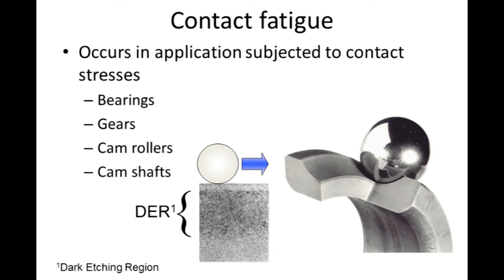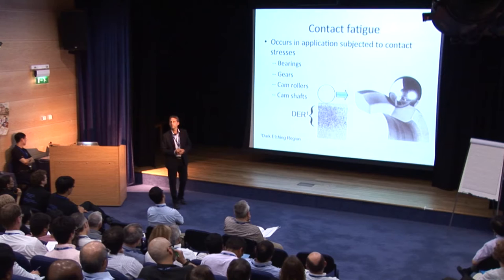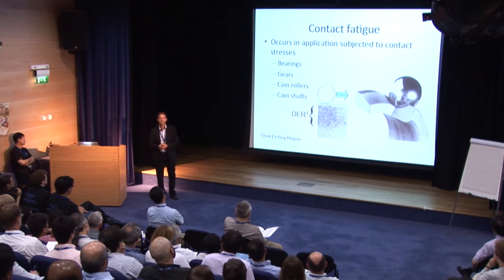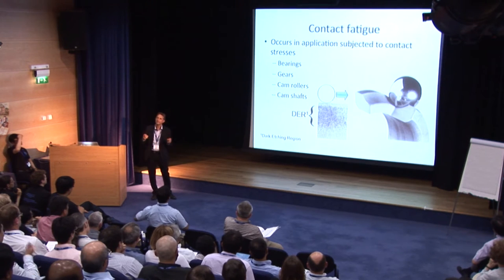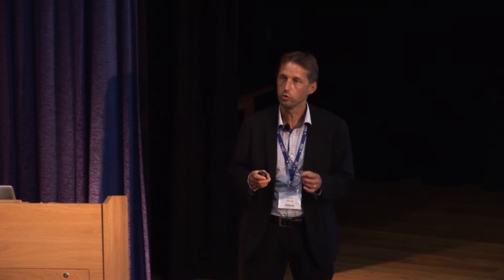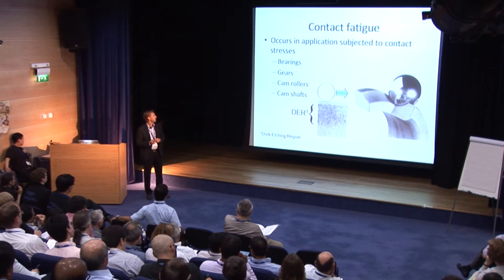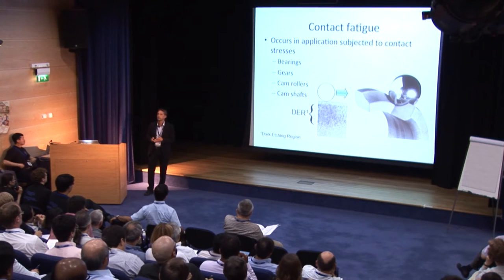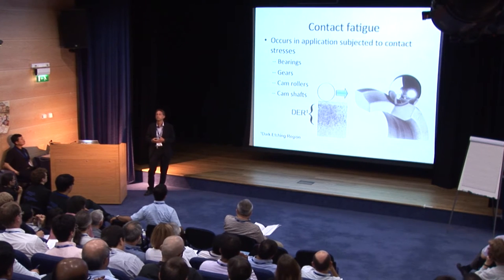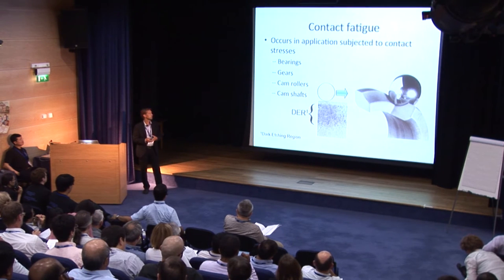There are a lot of different fatigue mechanisms. Sometimes you differentiate between contact fatigue and structural fatigue, some call it. I think, in principle, there are different test methods, but the general mechanism is fairly much the same if you look at it from the material point of view. I think contact fatigue is a good way of really looking at the matrix material. What happens with the steel matrix? Because you can see that quite well, because it's a rather slow process. We can run it for a long time.